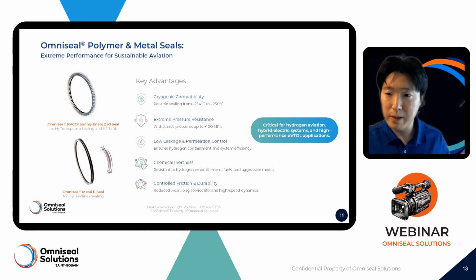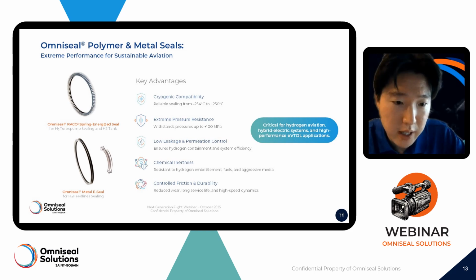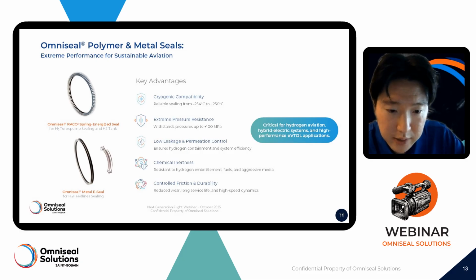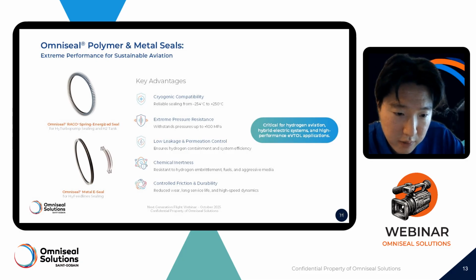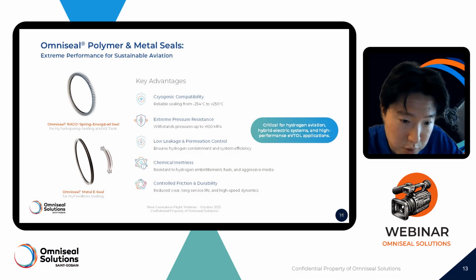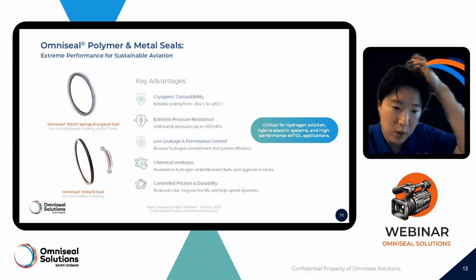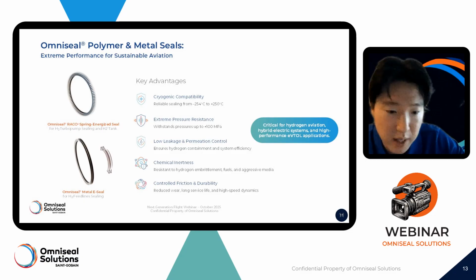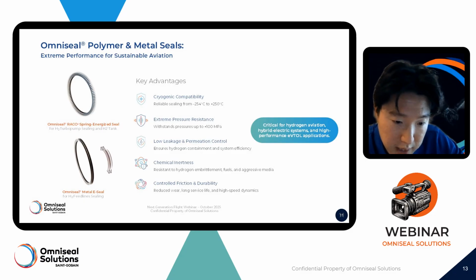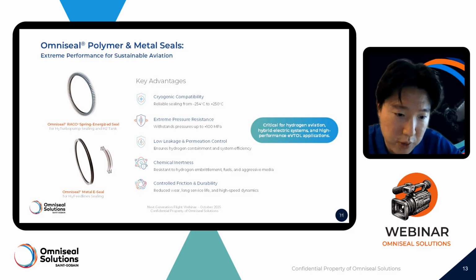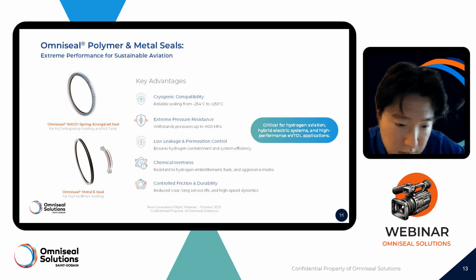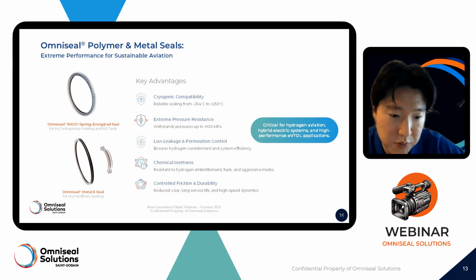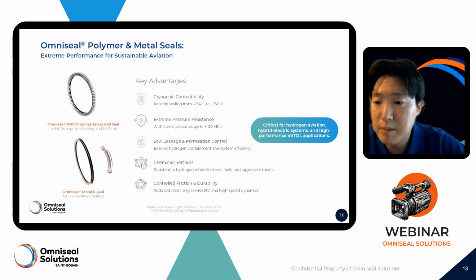So certainly when it comes to hydrogen sealing, we have polymer and metal seals that we can utilize. The key advantages here are with the RACO design, which is on the left, as you can see. We use it quite often for space applications as well, and as well as you see the metal E-seal that can be utilized. So, RACO seal, polymer seal for hydrogen turbopumps and tanks applications. We see a lot of metal seal application for hydrogen feed line sealing applications.